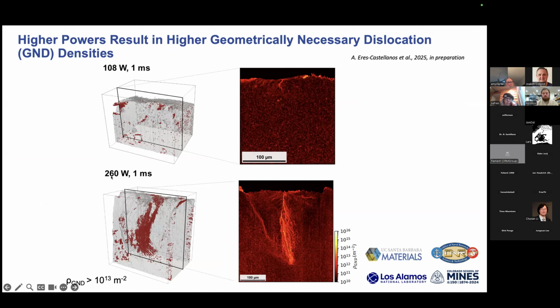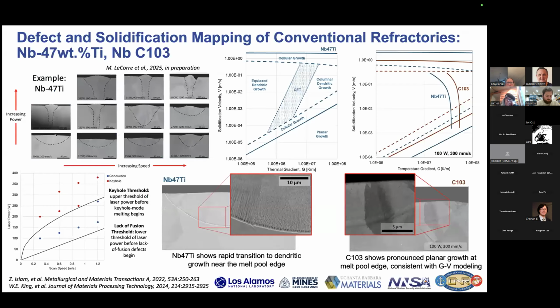And one thing that is pretty neat about this is you see for the high power condition, we tend to see a lot of GNDs present along the center line of the melt pool, which again isn't too surprising if you think about those processing conditions and the higher power conditions where we tend to see keyholing and a lot of keyhole collapse, producing again increased defect content.